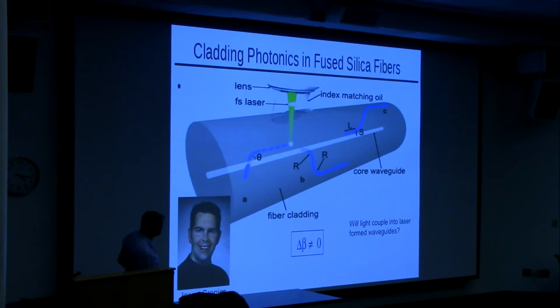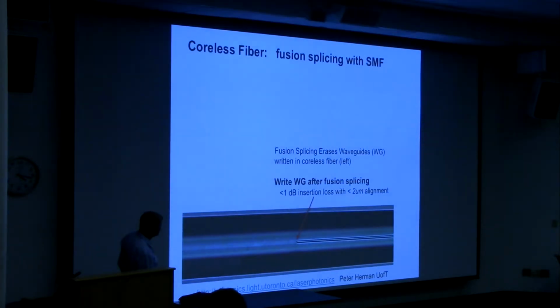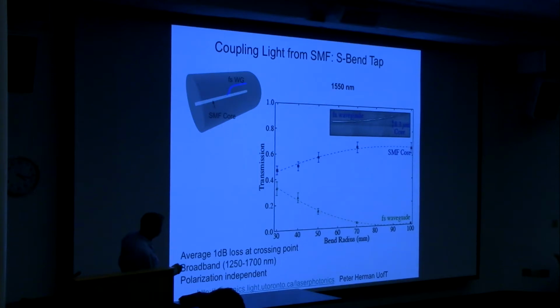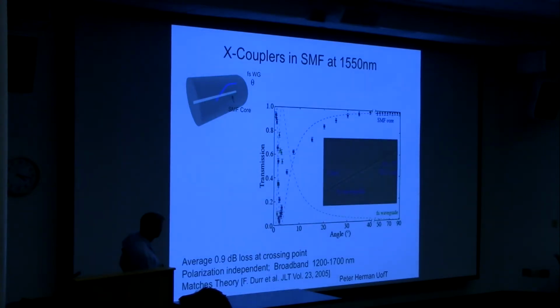There's Jason, quite a few years ago now, and he worked with other people in my group to make cross couplers, S couplers, directional couplers. They all worked, and it's a really good story. I'll skip this one. So for example, with S couplers, there's the core waveguide, there's the S waveguide, and as a function of radius, so changing the radius of the laser waveguide, you can see that the light in the femtosecond waveguide is growing as we make the radius smaller. So you can get light in and out, and that's a good story. It's important to be able to tap it in and out.